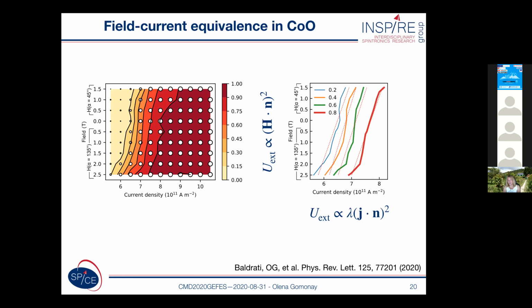which is confirmed by the theoretically predicted equivalence of field and current. And the color code in the left-hand side picture shows the probability of the switching phenomenon. However, what is also interesting in the theory of this thermomagnetoelastic mechanism is that the sign of switching, so this effective expression of the energy and sign of switching, depends not only on the magnetoelastic constant